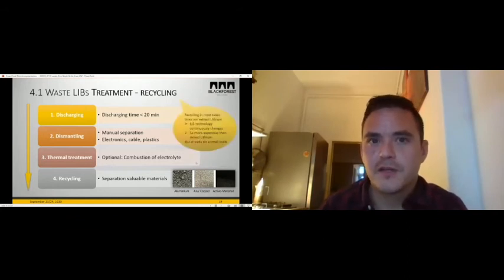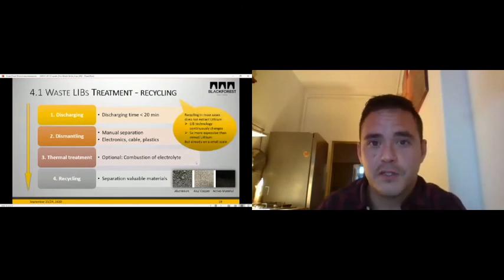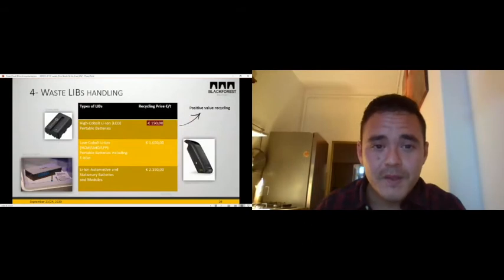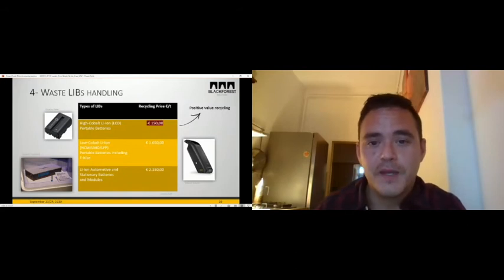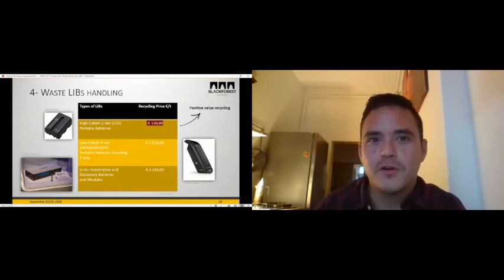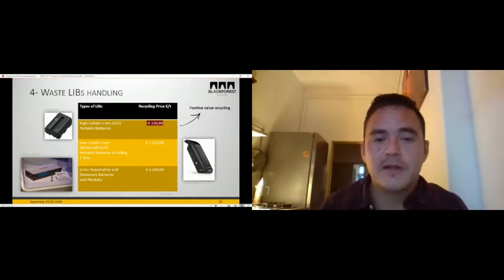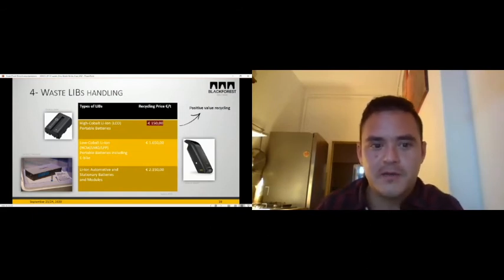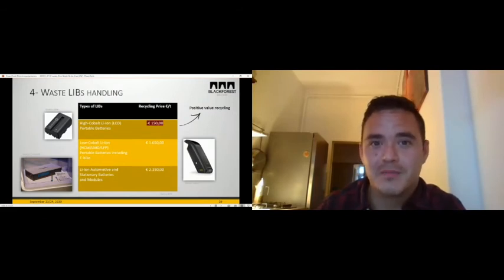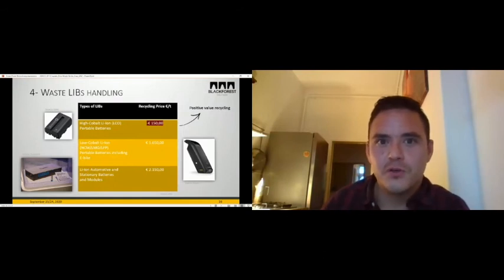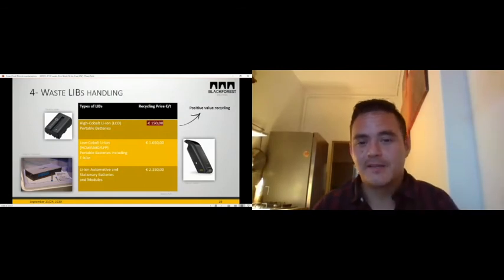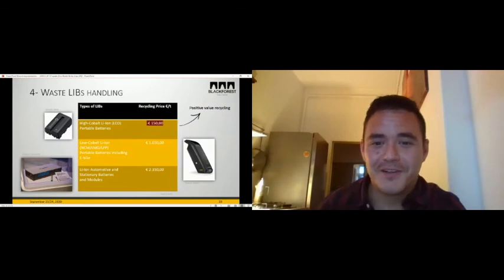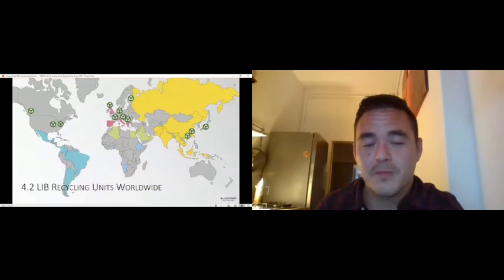Nowadays, we have different technologies, thankfully, but not so long as well, like a few years only. They work with different processes, mainly hydrometallurgical, which means that you dismantle the battery, you grind it, you dissolve the ingredients, and then you separate them in a much more efficient way than thermal smelting of the whole unit. This here is a very short overview of lithium-ion battery recycling, also a few years ago. Five years ago, you got 150 euro per tonne if we delivered high cobalt content lithium-ion batteries to the facility. The other types, we had to pay one to two euros per kilogram for the disposal, which is crazy.